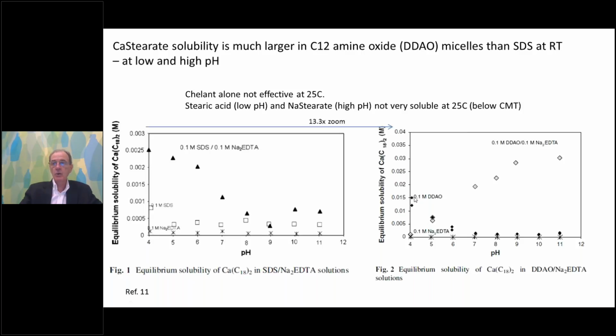On the right, we have a comparison with the amine oxide. Again, amine oxide alone, not so good. EDTA doesn't do anything, but the blend is significantly better at solubilizing calcium stearate than the SDS. There's a 13 times zoom on that y-axis there. So the amine oxide seems to be doing a really better job of dissolving the calcium stearate, and this is at 25 C. This is at room temperature. Sodium stearate itself, right, is not going to form micelles on its own.